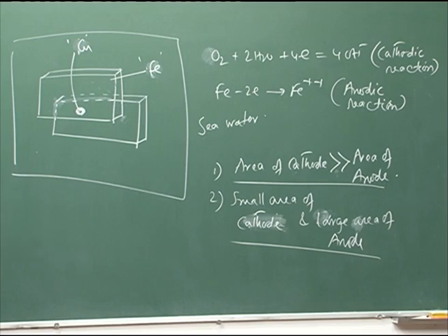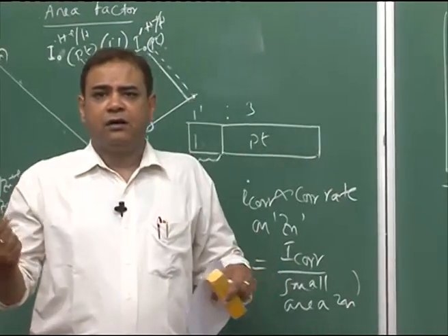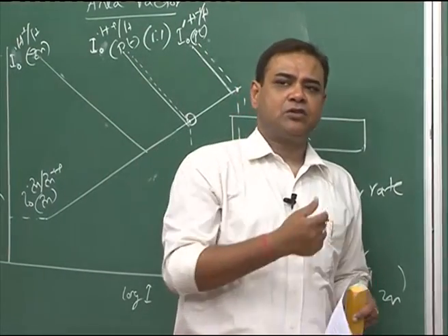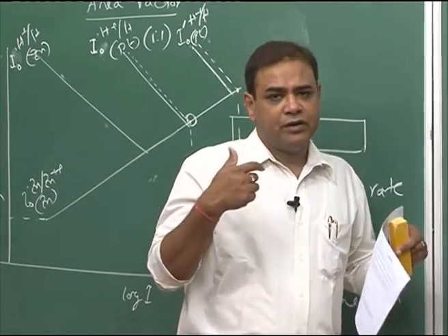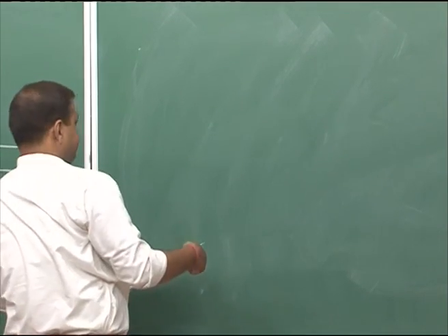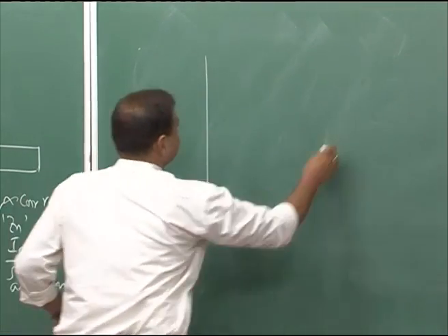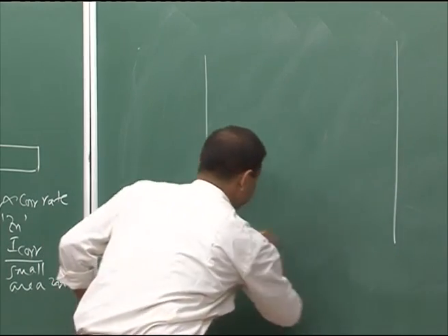This is one situation. The same happens if we have the Monel hull with the steel rivet. There also the hull strength would decrease because there would be aggravated corrosion on the steel rivet because of this unfavorable area factor. Now, we have one more classical example. Let us discuss that part. Let us say we have a water tank. This is my water tank.